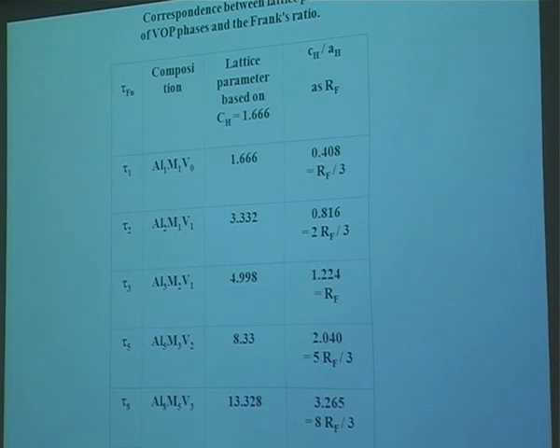Then we went on to look at these phases and show there is a correspondence in terms of the lattice parameter based with the Frank's ratio. Frank, as you might remember or recall, projected from a 4-dimensional cube to get a hexagonal phase, but it had a particular axial ratio. So in terms of that Frank's axial ratio, we have now, that is RF. If you divide by 3, you get that. If you multiply by 2 and divide by 3, you get that. So the whole series of tau phases are related to the Frank's ratio. So we are deriving, if you like, a 4-dimensional cubic crystal, all these phases with different axial parameters.